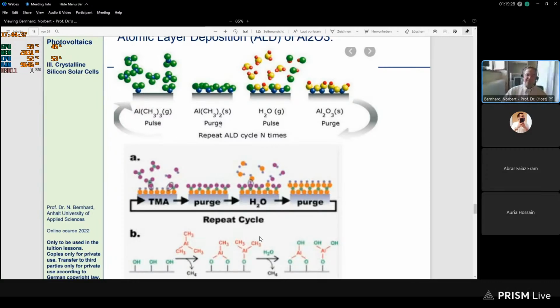First, we have a pulse of a gas, which is trimethyl aluminium. You see one aluminum atom with 3 methyl groups. That means the methyl group here is always one green sphere. And these adhere to the surface here, okay, as seen here. And everything that is not adhering to the surface is purged away.